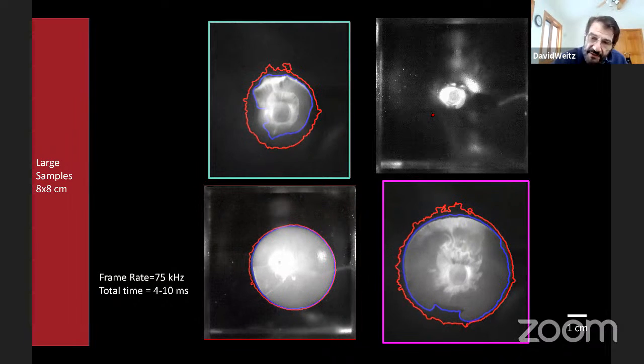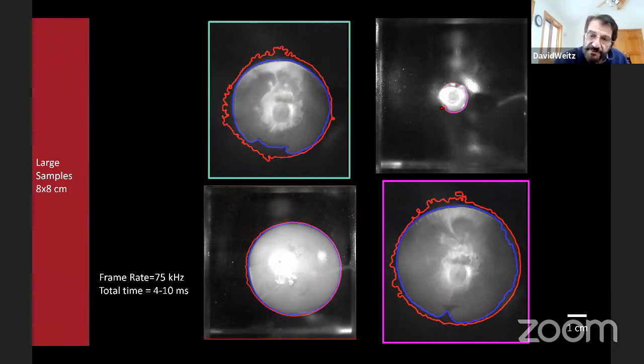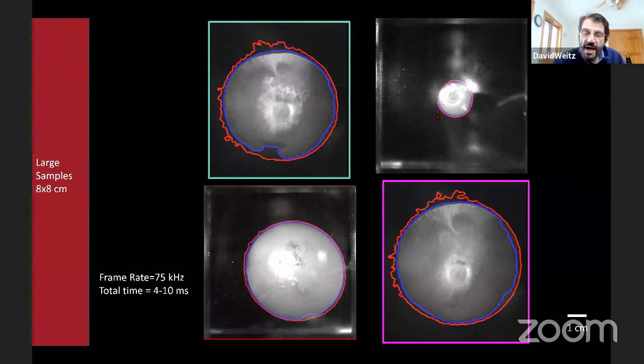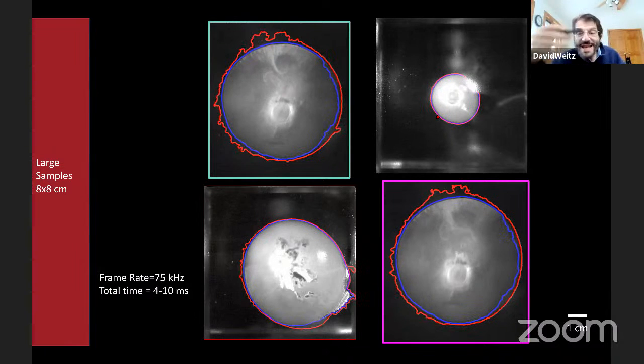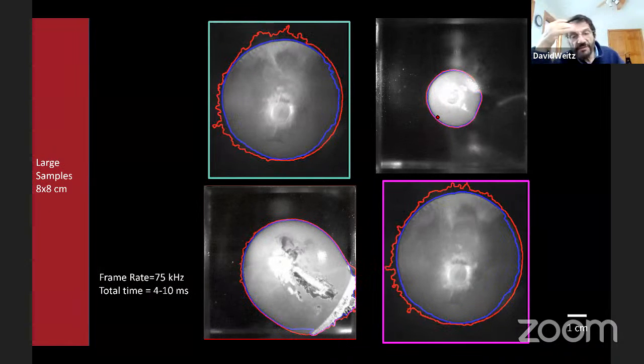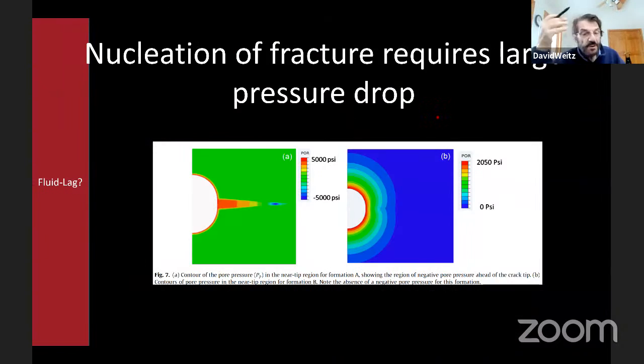This one's a little bit different. The fluid is always just behind the fracture. So this one has a slightly different behavior. We tried to understand that, and what we realized is that in the first 3 cases, we had to nucleate a crack. So we had to put large pressure, and finally a crack would nucleate. In the other one, the crack seemed to nucleate right away. We didn't have to overcome this nucleation barrier, and it nucleated right away.